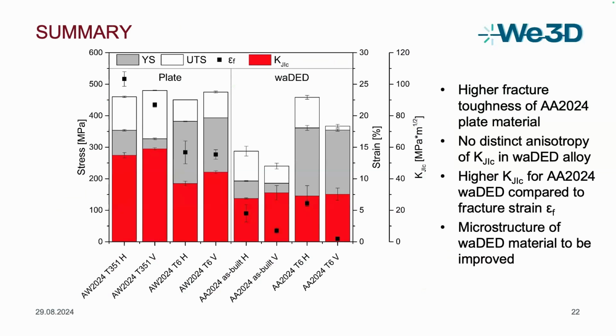Finally, here is the diagram with all the mechanical properties of this study. On the left side we have the plate material, on the right side the wire arc DED material. We see again that the mechanical properties of the plate material are higher, especially the fracture strain. On the other side, for the wire arc DED material, we have a lower strength in the as-built condition, which can be improved by the T6 condition. And we have a low fracture strain for all these conditions, especially in vertical direction. But the fracture toughness is at a very constant level of 30 MPa root meters and is not so far from the T6 condition of the plate material, which is about 40 MPa root meters.